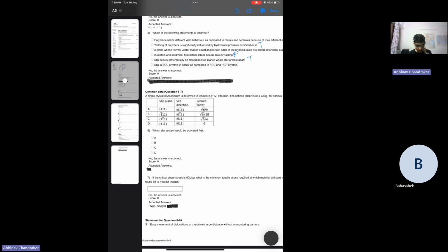Because in BCC the slip system is not as efficient as in FCC. FCC CRSS is lower, so in FCC slip is easier. So this is false. The yield strength is lower for FCC as a result.